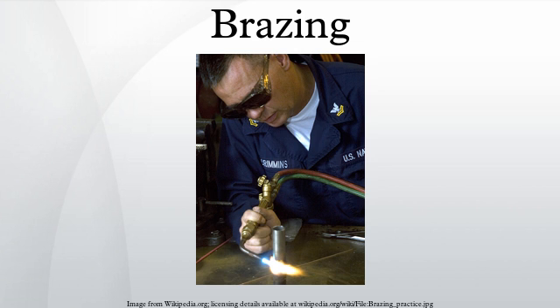Finally, brazing is easily adapted to mass production and it is easy to automate because the individual process parameters are less sensitive to variation. One of the main disadvantages is the lack of joint strength as compared to a welded joint due to the softer filler metals used. The strength of the brazed joint is likely to be less than that of the base metal, but greater than the filler metal. Another disadvantage is that brazed joints can be damaged under high service temperatures.